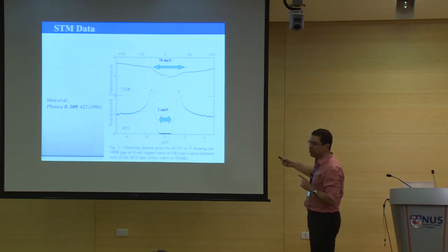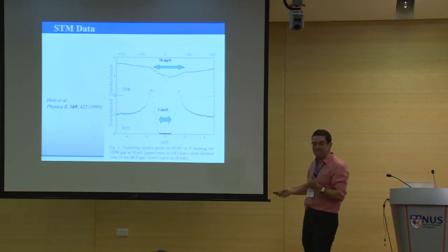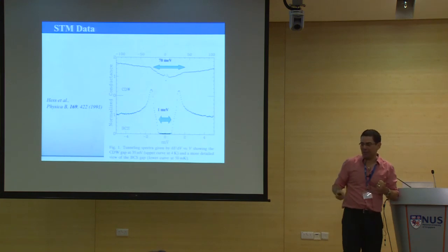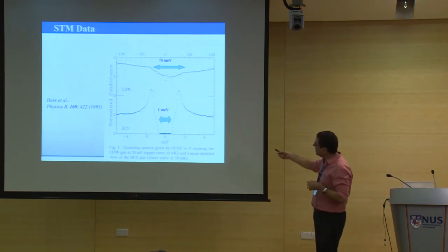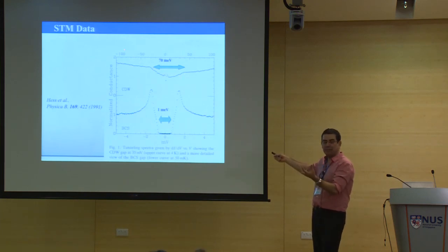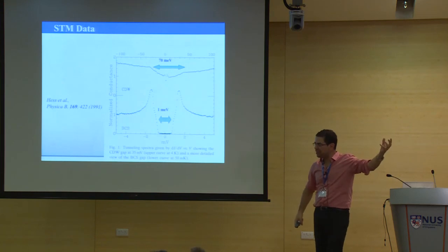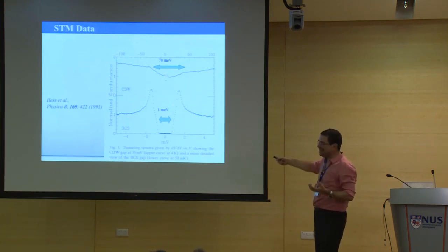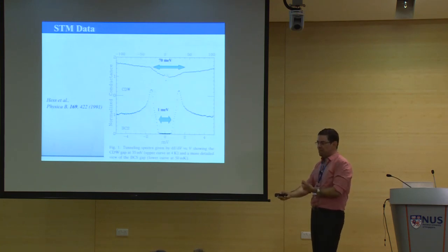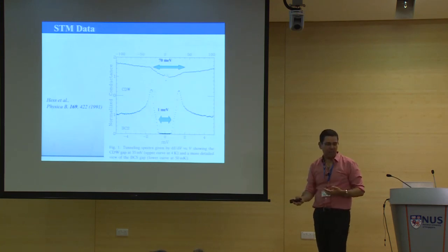And in fact, the density of states starts to drop actually 70 millivolts before. So even before, this is essentially what this means, that the density wave is already producing a big reduction of the density of states, which is consistent with the susceptibility measurements. Okay? But the superconductivity still develops on top of the charge density wave phase, because the system remains metallic.